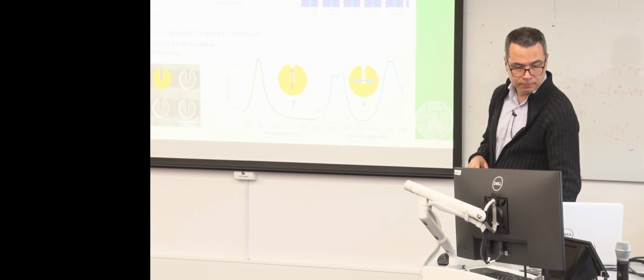If everything is really a point scatterer, then fabrication inaccuracies don't matter so much anymore. So if you have very good resolution compared to the size of the wavelength, then I think there's promise. If you are at the limit, a third of the wavelength, a fifth of the wavelength or so, then you need really good fabrication, otherwise you have issues.